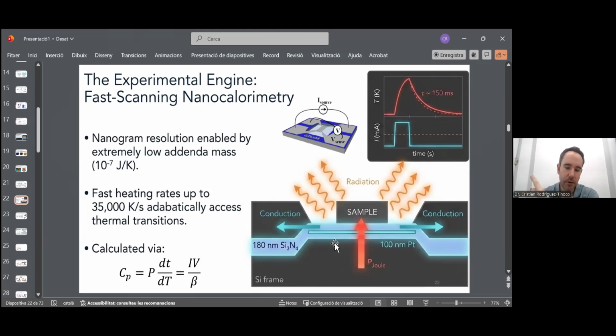Quasi-adiabatic, why? Because we don't have temperature or power losses by convection, because remember, we work in ultra high vacuum. We don't have losses by conduction because we are injecting the power so fast that there is no time for thermal diffusion to bring this heat into the frame of the device. And there are no losses by radiation because we typically work in a temperature range where radiation losses are negligible. Remember, the glass transition temperature is 330, 350 Kelvin, very close to the ambient temperature. So this is a quasi-adiabatic measurement, and then we can calculate the heat capacity.